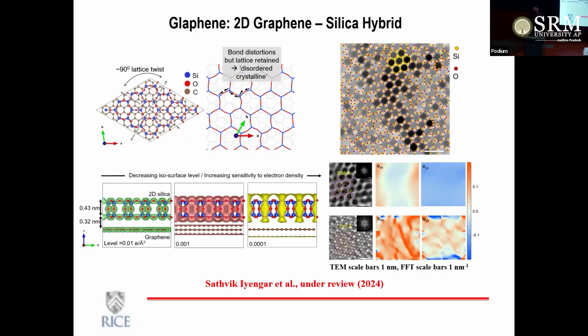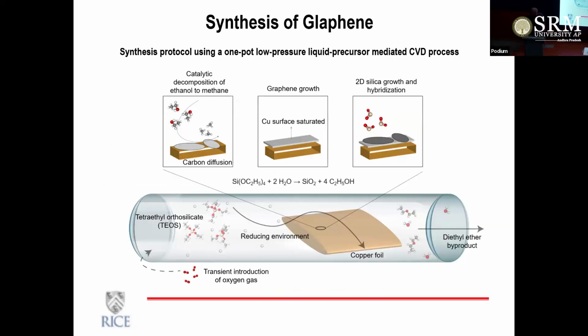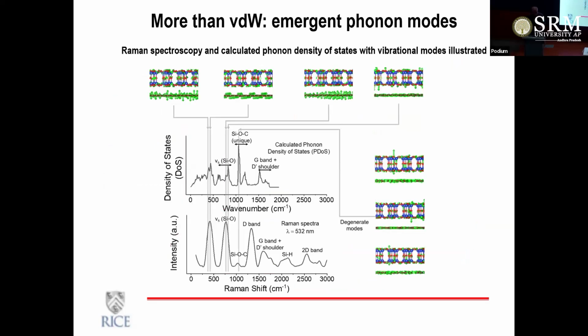Actually, you can make these hybrid silica graphene layers by vapor phase deposition using a particular precursor, a single step method. I'll quickly go. But again, by looking at the phonon modes in the structure, and also detailed Raman spectroscopy and IR spectroscopy and so on, basically, we have proven that this is actually a unit that is different from both graphene and silica, right?